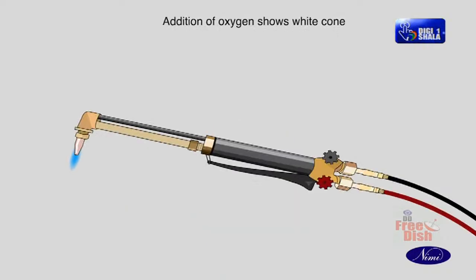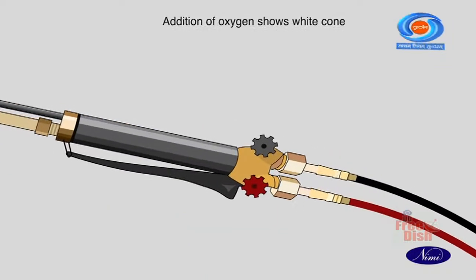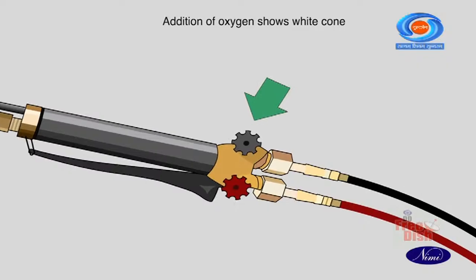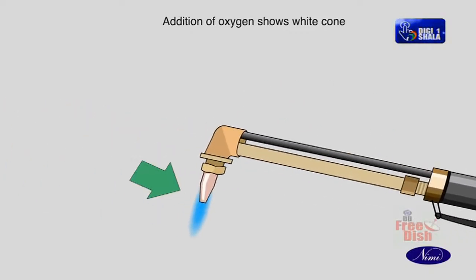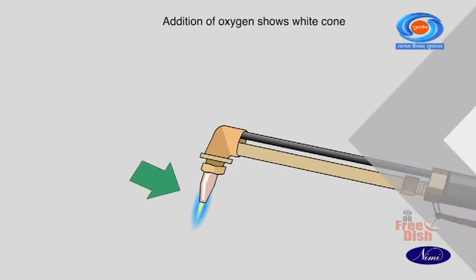Now, observe the flame and add oxygen by opening the oxygen control valve of the blowpipe. Now, a bright white cone starts appearing at the tip of the nozzle.